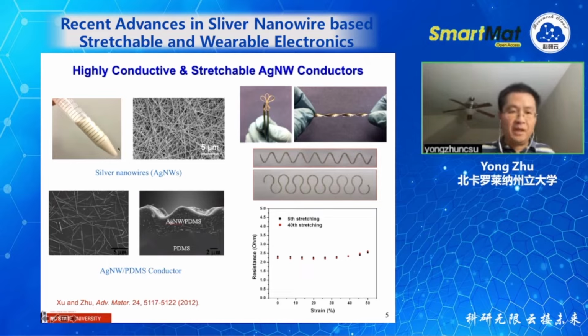You just drop cast the silver nanowire solution and then you form this nanowire network structure. Then you coat a layer of elastomer material like PDMS on top, in the liquid state, and the PDMS infiltrates through the nanowire structures, and then you let it dry and peel it off. Then you form a composite structure, in which the nanowires are below the surface of the elastomer, as we can see from the cross section here.